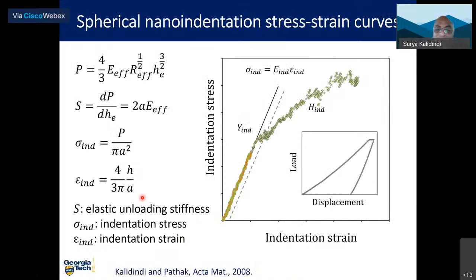The technique that we have largely spent our time on for mechanical properties is indentation. So this is an indentation stress strain curve. This is raw data. You get a load displacement curve. These are spherical indenters, not sharp indenters. The advantage of spherical indenters is that there's a very small elastic portion. By looking at it, you can't tell where it is, so you need an analysis protocol. And we developed the right analysis protocol to identify this elastic portion. But it's extremely small. It's tiny. You can hardly see it.